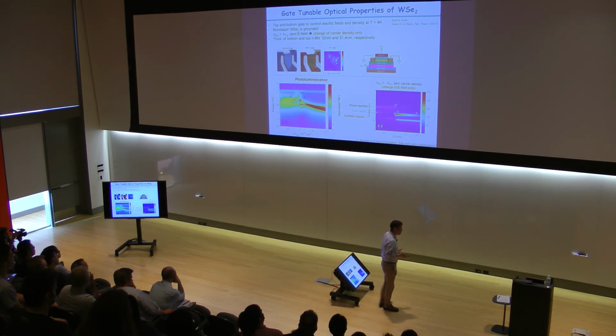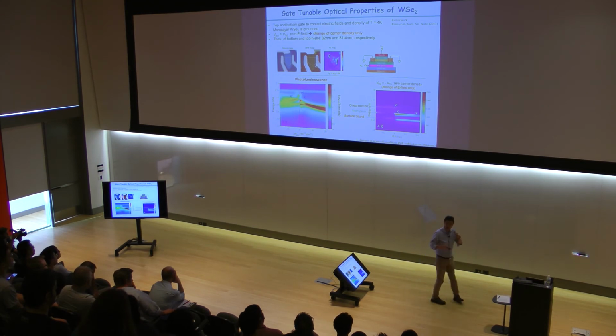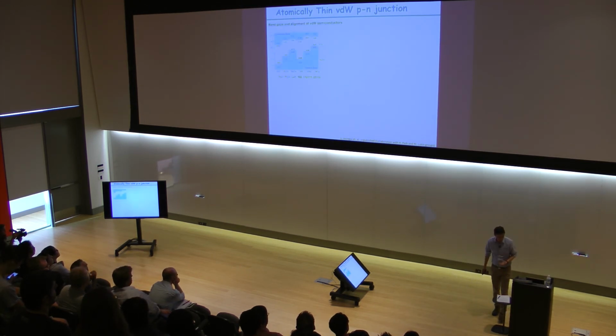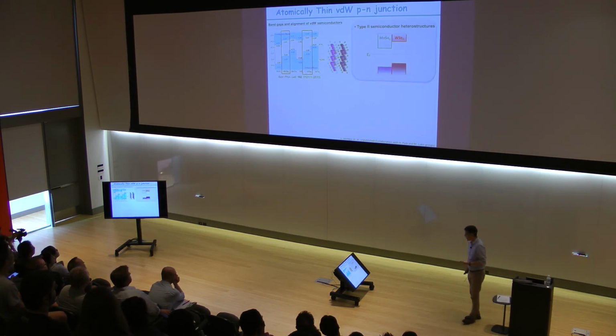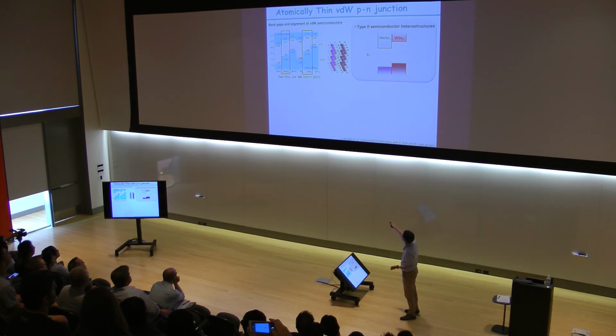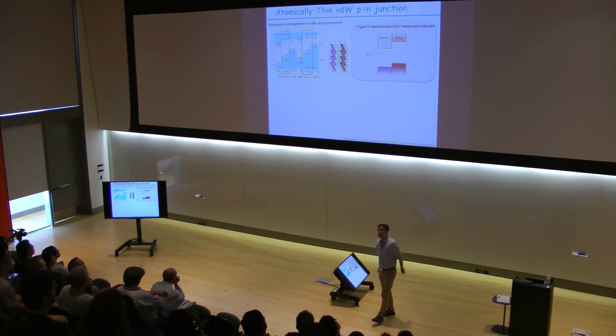While the two-dimensional system we create is a completely two-dimensional electron system, one can create a rather semi-three-dimensional system by heterostructuring. I told you that we can create p-n junctions by just choosing different types of materials. In this particular case, molybdenum disulfide and tungsten diselenide, put them together. It's a type 2 band alignment. We can create these structures. I showed you before that this behaves like a p-n diode.